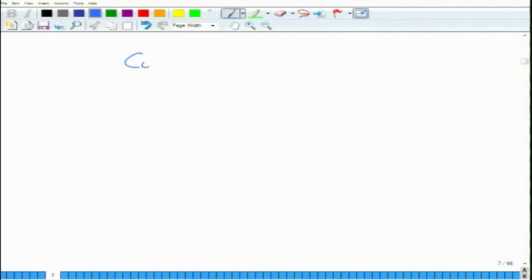So you have to choose a radiation for iron containing materials whose wavelength is higher than the wavelength of the iron edge. So for this we choose, for example, cobalt K alpha. Cobalt K alpha has a lambda which is 1.789 angstrom.